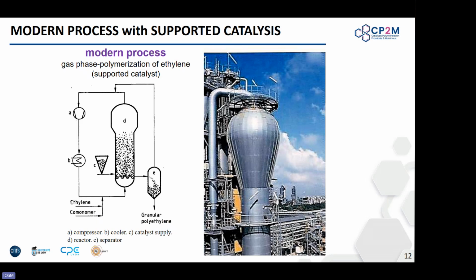These are more modern processes. Okay, it's a gas phase reactor. This is very close to the Unipol process. Okay, and it's a fluidized bed reactor. So you have particles of catalyst. Okay, you pressurize with the gas. It's a fluidized bed, and then the particle of polymer grows around the catalyst particle, and then you have a separation, and you can also separate the fines. You can recirculate. There are many variations now. This is a simplified process, but it's just to tell you that this came to be just because we realized that we could support the catalyst, and I will explain to you how you can support this catalyst.